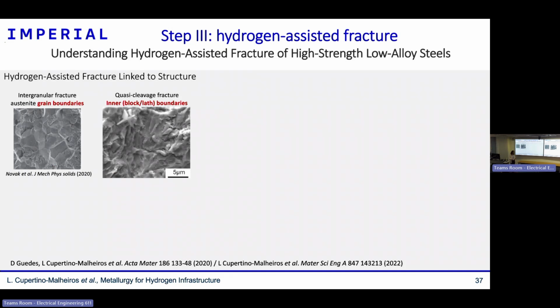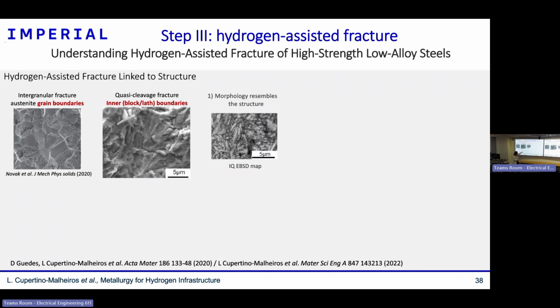I also tried to link this quasi-cleavage fracture that you saw with hydrogen flux with the structure of those steels. What I noticed is we didn't have the type of fracture where you see grains at the surface, which would indicate that the fracture is intergranular. We have this fracture morphology. But when I compare with the structure of those martensitic steels, they have, in addition to those boundaries, lots of inner boundaries. And I can see that the fracture surface resembles very much the structure of those steels. So this is an indication that the fracture is happening at the inner boundaries.